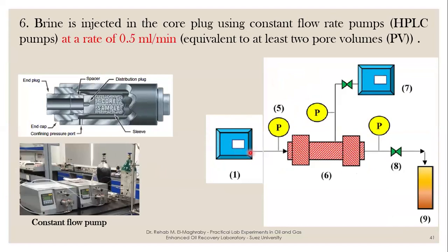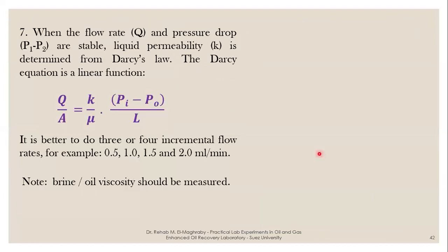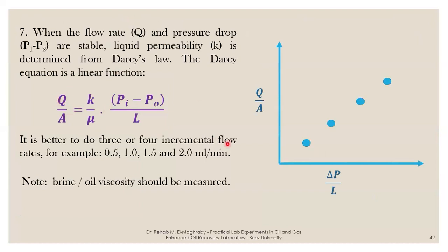You will have the flow rate, the pump injected at, for example, 0.5 milliliter per minute, then 1.0 milliliter per minute. So you change the flow rate of the liquid that you are injecting. Now you can calculate and draw because you did different tests at different flow rates. You have the flow rate divided by the area, which is constant, the flow rate we are changing, and then delta P changes according to the change in the flow rate.